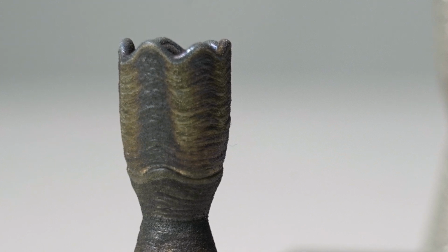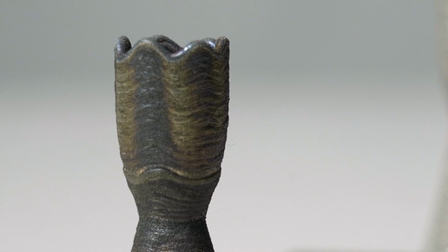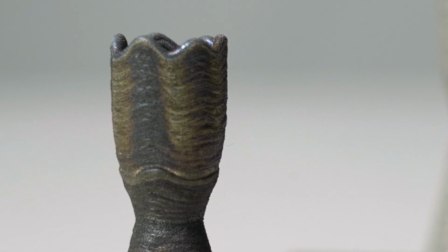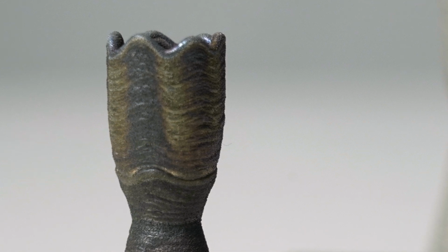Yeah, great observation, Pete. And I think typically what you would do, just like in laser powder bed fusion, right? You don't always start and stop at the same point. And so in this case, you can actually see we start and stop at each layer. We sort of increment over and start and go, increment over, start and go. And guess how many times we do that? It's the same as the number of nozzles there. And so as you start at different positions and go around, because that heat transfer varies, you're going to start getting slightly higher peaks earlier when it's not as hot versus later. If you can't get all that heat out quick enough, the end result is the layer height is higher versus what you had planned. And it's going to progressively get worse and worse as you increment around and do multiple starting points for each different layer.